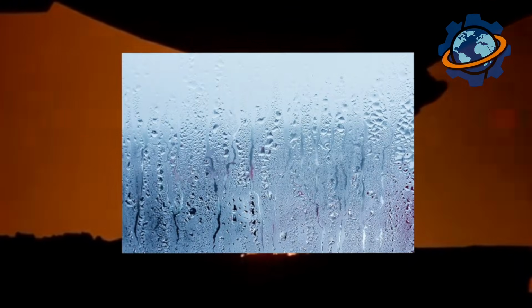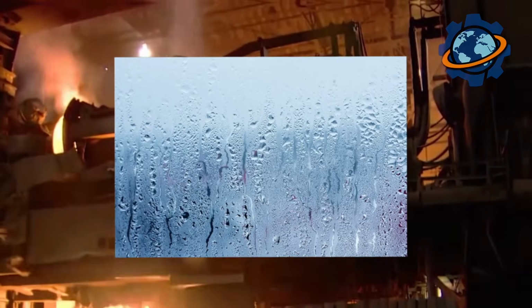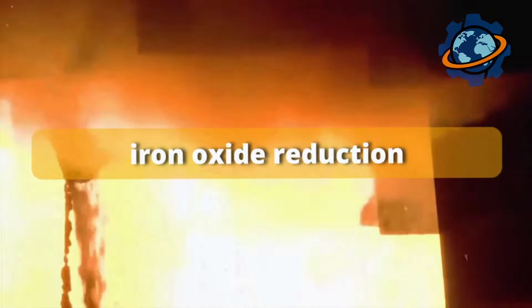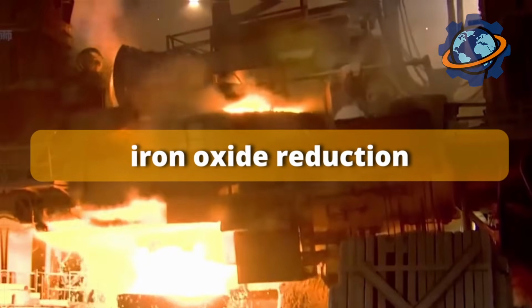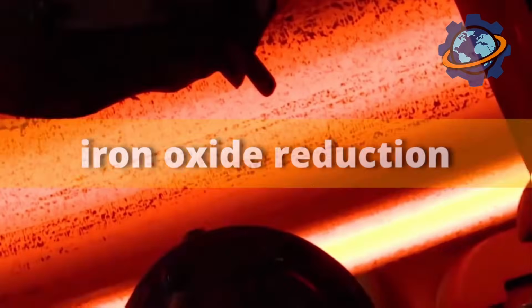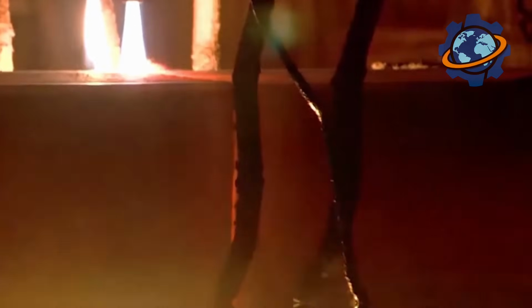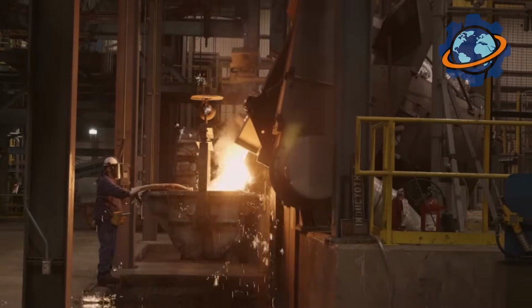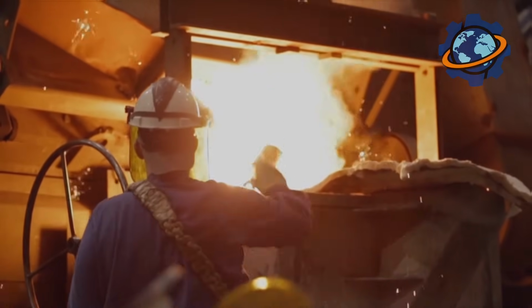First, moisture leaves the ore. Then, at 930 degrees, iron oxide reduction begins. Carbon from coke strips away oxygen. At 1,800 degrees, ore becomes spongy iron. At 2,700 degrees, iron melts. Drops of molten metal flow down. At the furnace bottom, molten pig iron accumulates, an iron alloy with 4% carbon.